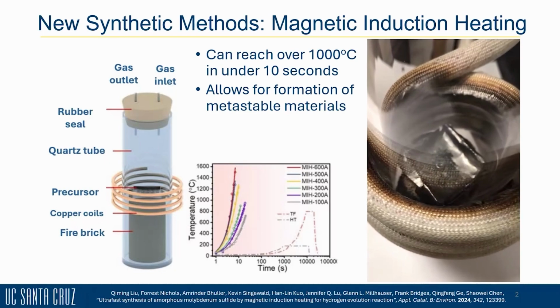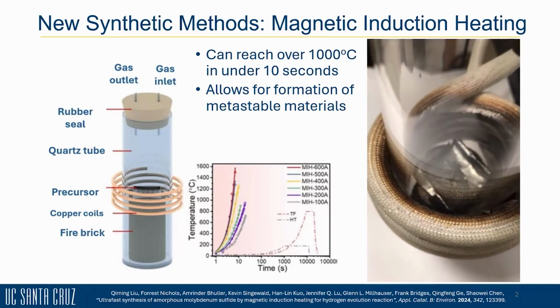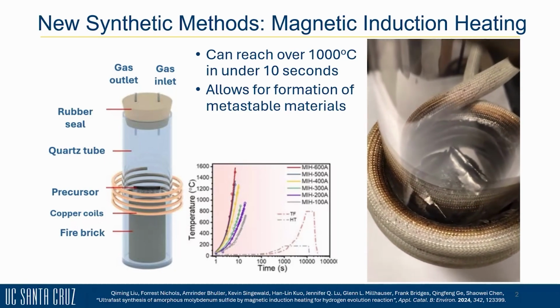This is done by utilizing strong magnetic currents to heat up an iron sheet to over 1,000 degrees Celsius in under 10 seconds. This rapid heating and cooling can be used to generate metastable materials, and we used it along with copper chlorophyllin to produce a graphitic material which is highly conductive with copper N4 active sites, effective for the two-electron oxygen reduction reaction.